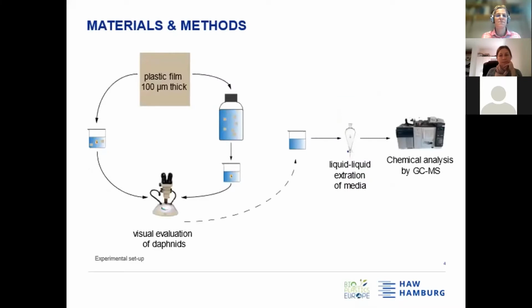So here you can see the experimental setup for the chronic daphnid and acute daphnid test. We have thin plastic films from the bioplastic materials, which were about 100 micrometer thick. First of all, we cut them into small pieces of 1 by 1 centimeter. One part of these films was tested directly in contact with the daphnids, as you can see on the left side. We put the small plastic sheets directly into clean beakers and added some media, and then we put the daphnids into the test.